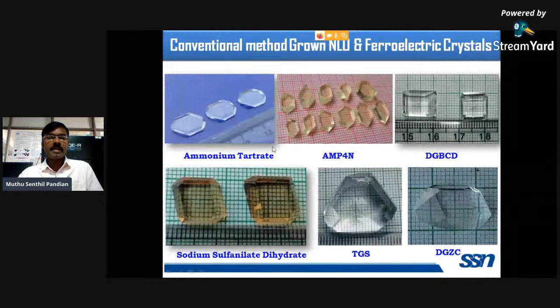So these are some of the conventional method grown ferroelectric and nonlinear optical single crystals. If you see any one of the conventional method grown crystals, all the crystals have different planes, facets, growth sectors, and growth sector boundaries. But from the application point of view, the device point of view, only the phase matchable portion is useful, and other portions are wasted after cutting the phase matching angle. For devices like frequency doublers and optical parametric amplifiers, phase matching needs to be achieved. Otherwise, the conversion efficiency would be very low.